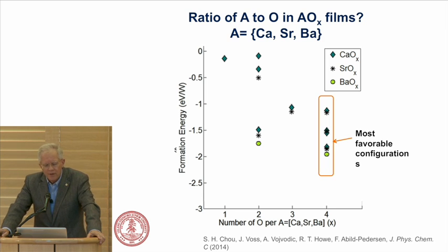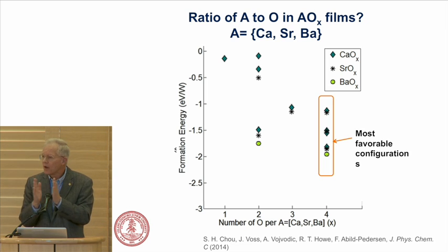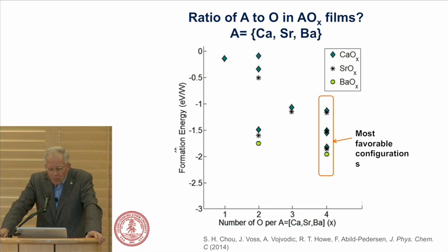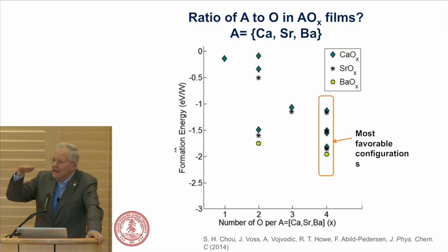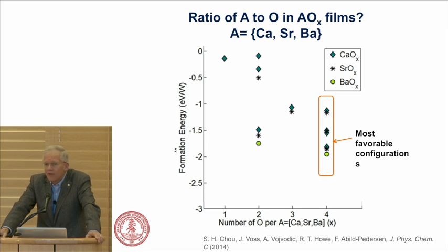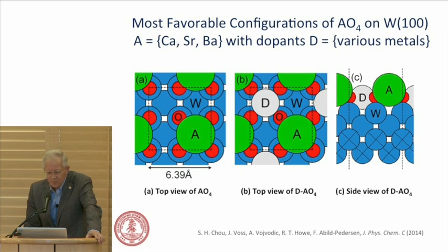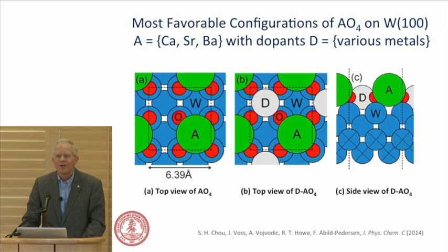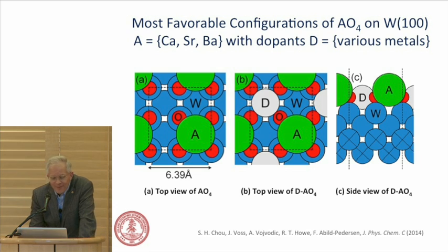But in context, the fabrication technology where you would engineer the composition of these would be, from my perspective, done using atomic layer deposition, which is a very powerful tool. We are currently depositing strontium oxide on tungsten, for example, but there's work in the literature where you would nano-laminate these materials between strontium and barium and calcium, and then do post-processing to center and dial in that composition very, very tightly.